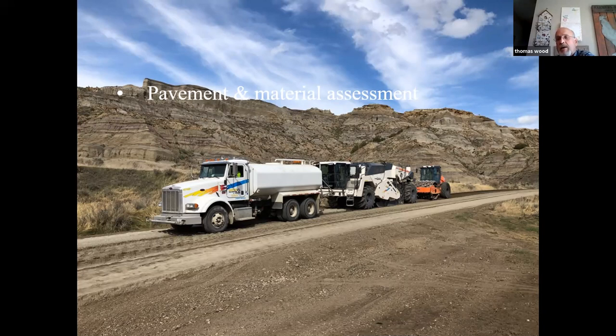When I was at WSB, we had one city that did a lot of FDR in their curb and gutter area, and they ran 3.5-4 inches of bit and 3.5-4 inches of gravel. And then after they ground it off, then they pulverized it. They would come in and have the contractor pick up the 3 inches of surplus material and put it in the city stockpile site. And then when a developer would come in to build a new subdivision, the city would sell them that material to the developer to use underneath the street. And it was a win-win for the city.